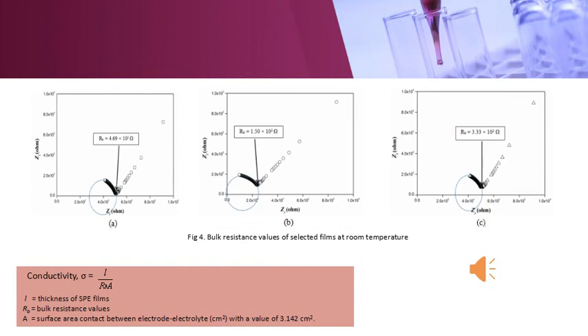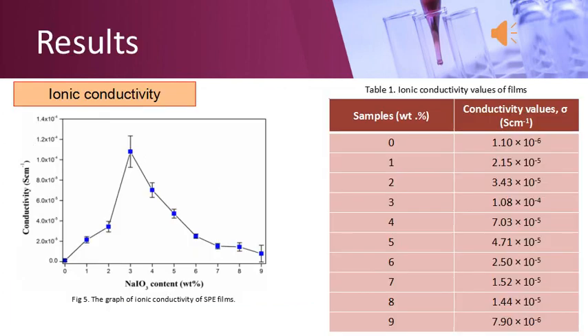So the value of bulk resistance for each sample was obtained from the Cole-Cole plot, and it will be inserted into the formula to calculate the values of conductivity. The capability of an electrolyte to conduct electricity is examined by using the EIS technique. Ionic conductivity of cornstarch sodium iodate is shown in figure 5, while the conductivity values are summarized in table 1.